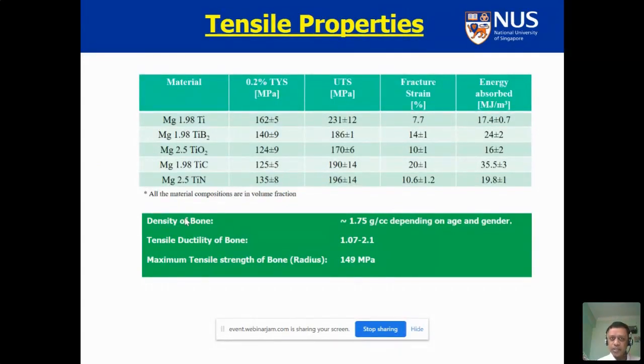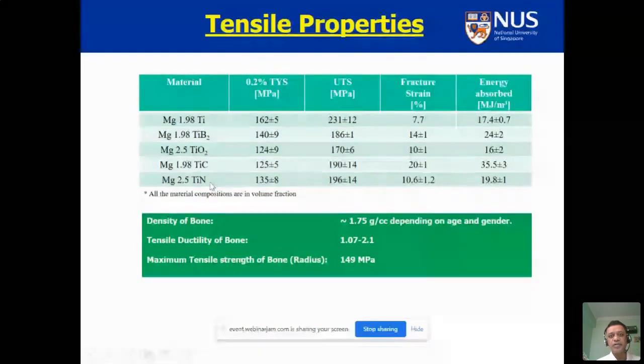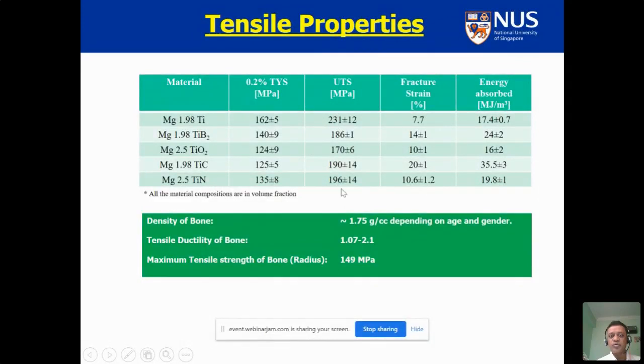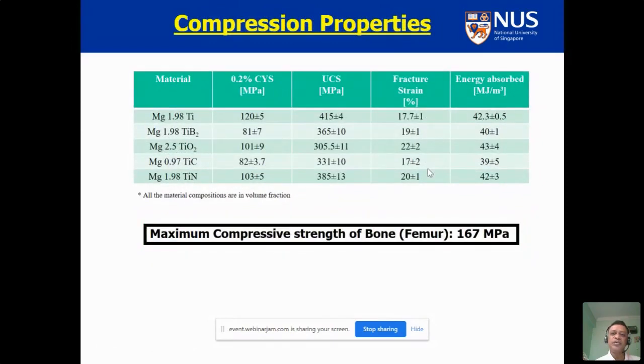So before you put an implant in the body, you have to see that its strength is at least exceeding that of the bone, and also the ductility, so that you are putting in a material better than bone. If you look at this, we tried many nanocomposites reinforced with titanium, titanium diboride, titanium dioxide, titanium carbide, and titanium nitride. In all the cases, their strength is more than the strength of the bone, and the ductility of the bone is only up to 2%, and these materials have a much higher ductility. That means these materials are much stronger and tougher than the bone. And from a mechanical point of view, yes, you can put them in there. Similarly, in compressive properties, they are all superior when compared to the bone.